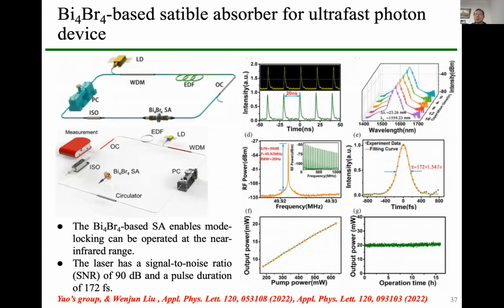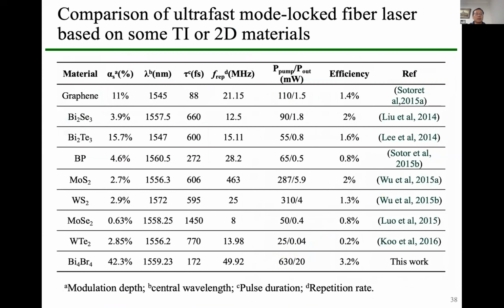Because this material has very interesting properties, we prepared a bismuth bromide saturable absorber, which enables mode locking operation in the near infrared band. So it may be useful for high power, ultrafast photonic devices and further development of photonic applications. So we have applied some patents on these applications. So you can see that this property is very, very nice.